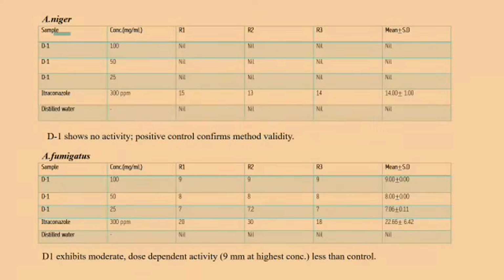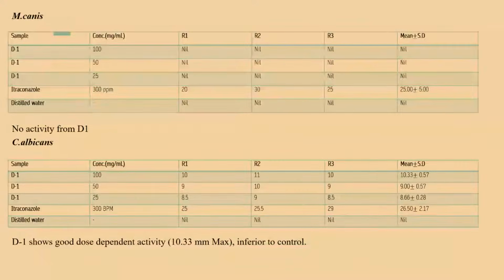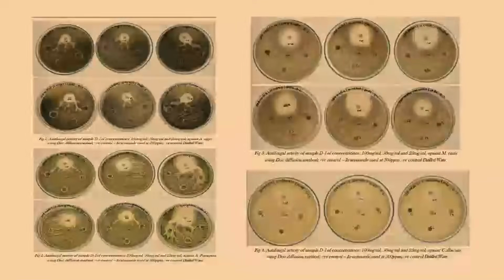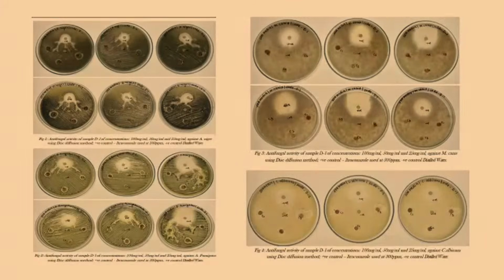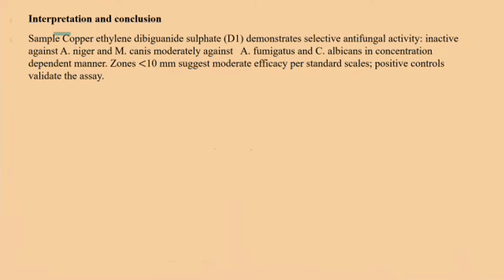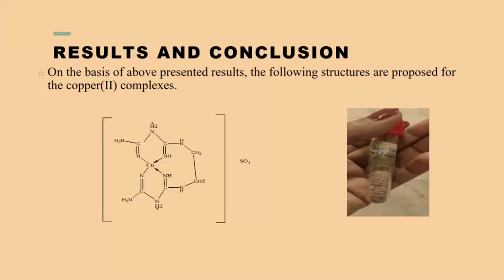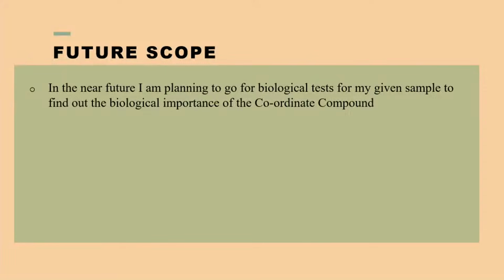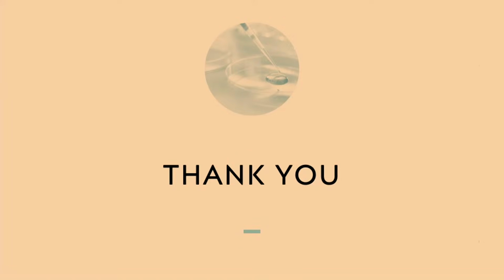This is the tabular form for the different fungi that I have studied, in which Aspergillus niger shows no activity, and Aspergillus fumigatus shows moderate activity, around 9 millimeters at high mg per ml. M. canis also shows no activity for my synthesized compound, while Candida albicans shows a good dose-dependent activity in terms of zone of inhibition. This is a photograph of the 3 concentrations that I took for the 4 fungi. So I can conclude that this is the structure of the synthesized complex, and the real photograph of the metal biguanide complex. In the future, I am planning to broaden the biological tests for this synthesized compound. Thank you.